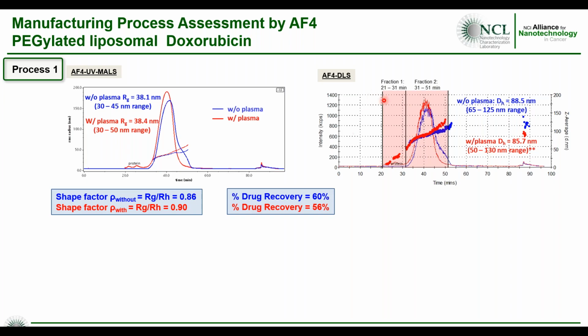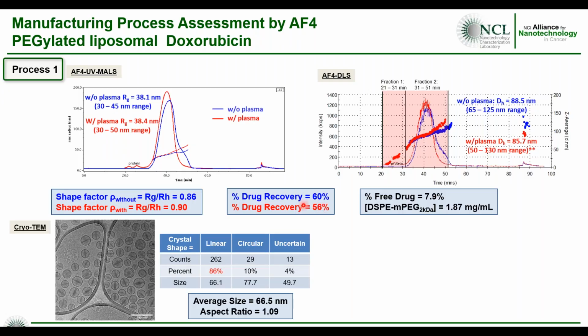We also looked at the collection of these peaks to look at drug recovery, about 60% in this case. We did other analysis to look at the free drug, 8% in this case, as well as lipid PEG content. What's interesting here is we did cryo-TEM on these samples, and an example is shown here. These are around 66 nanometers with an aspect ratio of roughly 1, so they're nearly spherical. What's interesting, though, is because you have doxorubicin crystallized in the interior, you can look at the crystal shape morphology, and we calculated the linear and the circular drug shape morphologies from the TEM micrographs. Based off of process 1, we're seeing about 86% with a linear crystal shape.